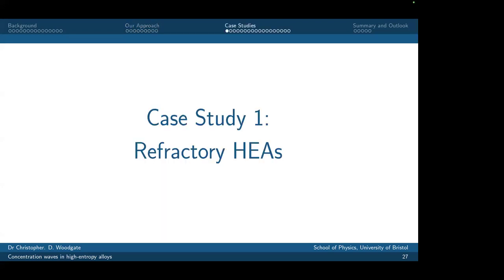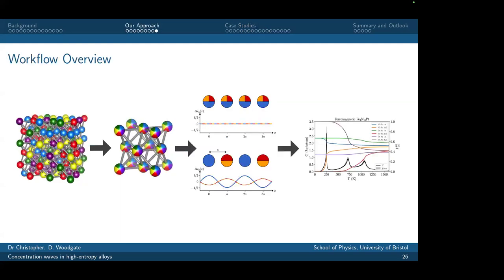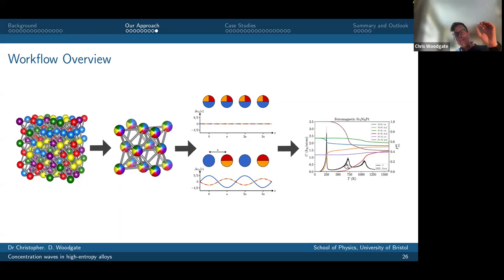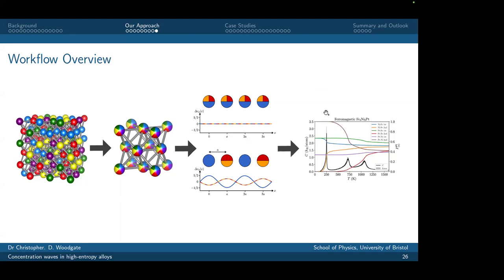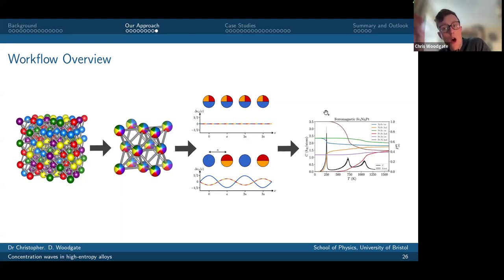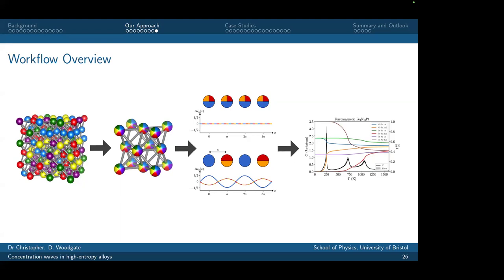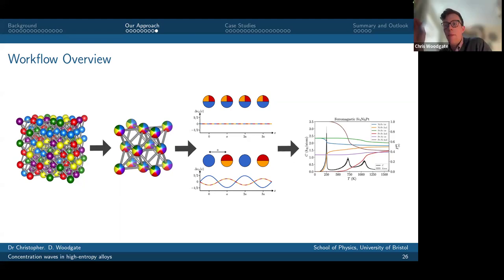Sorry, can you briefly comment on the specific heat? What are the three peaks? Are the higher ones chemical ordering? This is only looking at chemical orderings. So what I'm plotting is the configurational contribution to the specific heat capacity. And here, it turns out that there are three distinct orderings that emerge in that particular alloy.